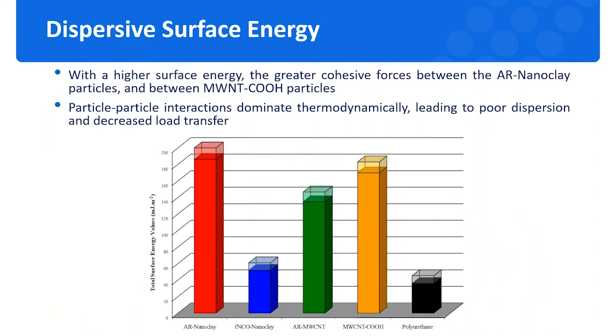So here lists the surface energy of all the different components. Among the nanofillers, the nanotube sample is energetically more active due to the aggressive oxidizing of the acid treatment. So this may have introduced more defect sites and also shortened the nanotube length. And with a higher surface energy, the greater cohesive forces between the nanotube particles will lead to poor dispersion or decreased load transfer to the nanofillers. And also the significantly lower surface energy of the treated nanoclay sample indicates a dramatic passivation of the surface with those kinds of functionalized treatments on the surfaces of these nanofillers.